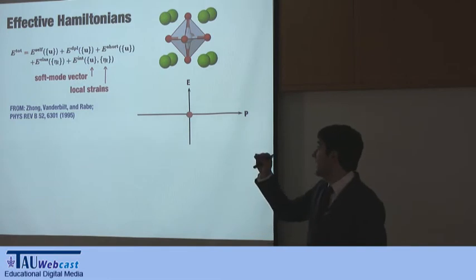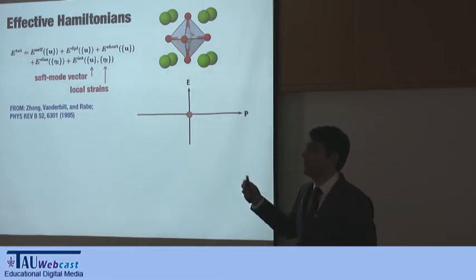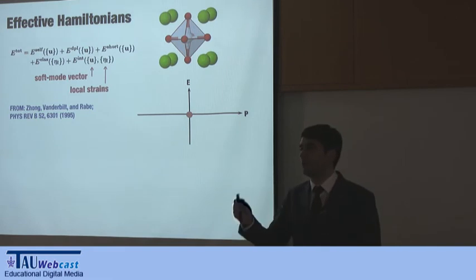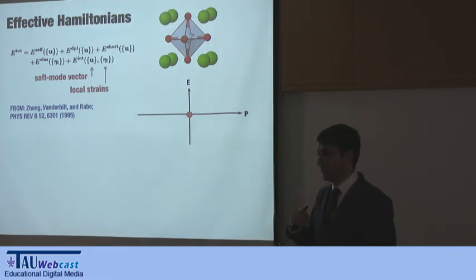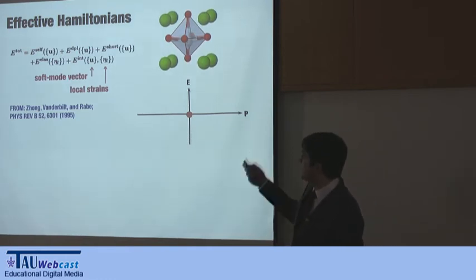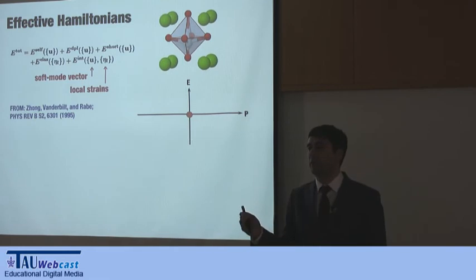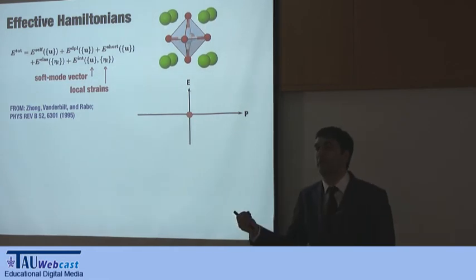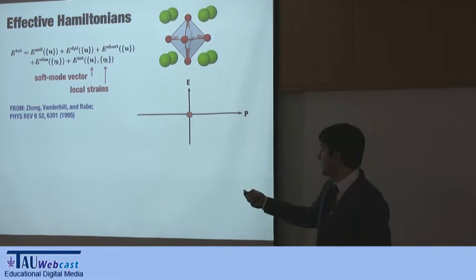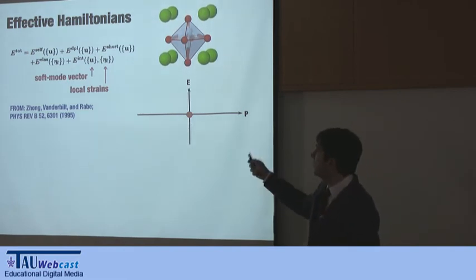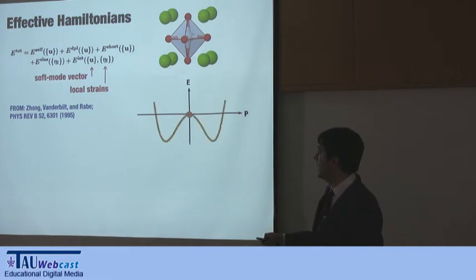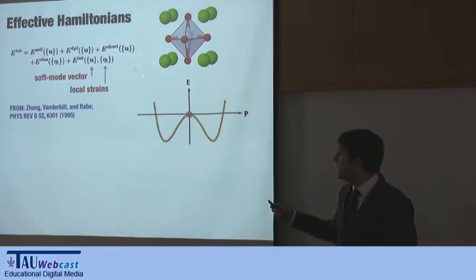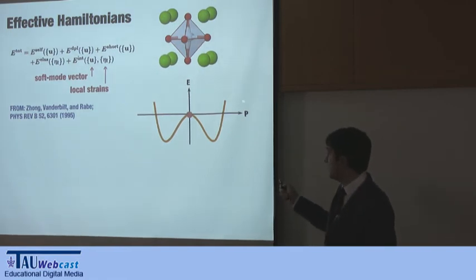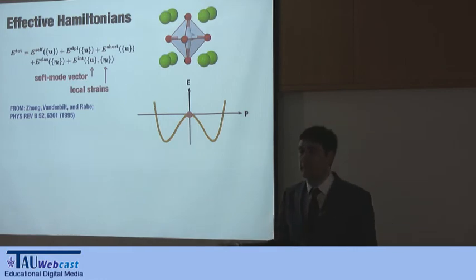So the cubic is stable at high temperature, but there is a transition, and the mode condenses. The atoms go through the motions given by the mode. In this case, the mode is something like this. It's going up and down, vibrating there. If you lower the temperature enough, the structure will go down. So this is the energy of the perfect cubic structure. And below some temperature, if you displace the atoms according to that mode, you lower the energy. Okay? And you can compute the polarization and map the energy versus the polarization.